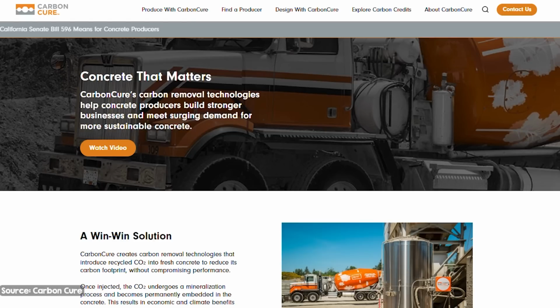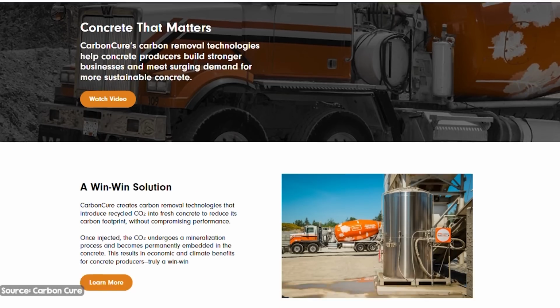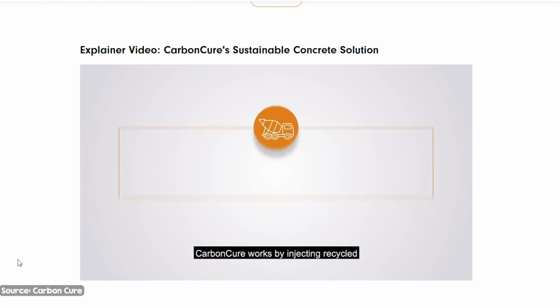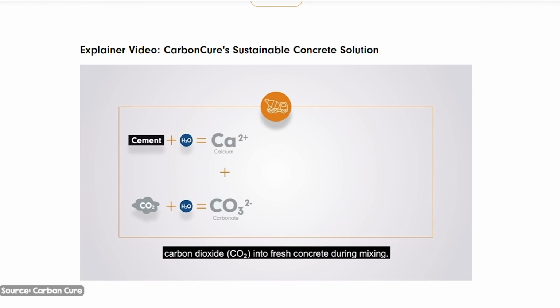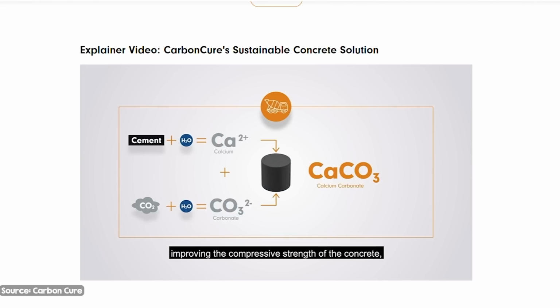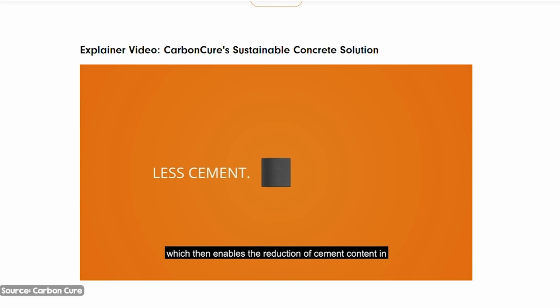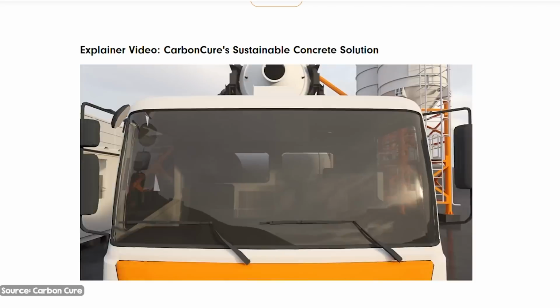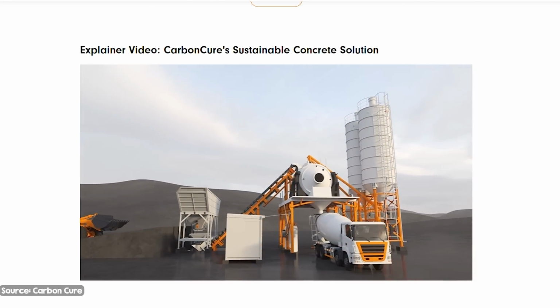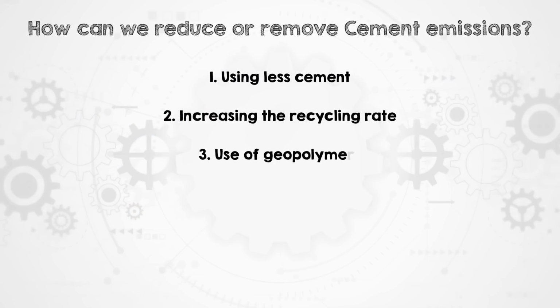There are also several technological solutions for reducing cement usage. A company called Carbon Cure has developed a technique that involves injecting CO2 into concrete. They claim that this actually increases its strength, and because it's stronger, around 4 to 6% less cement content is needed. And as an added bonus, the injected CO2 stays there permanently, with about 13 kilograms of CO2 per cubic metre of concrete sequestered.